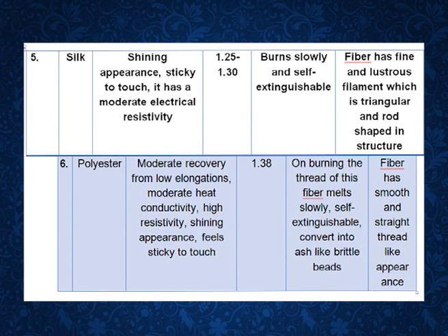Then is the polyester. Now it has a moderate recovery from low elongations, moderate heat conductivity, high resistivity, shining appearance, feels sticky to touch with a specific gravity 1.38. On burning, the thread of this fiber melts slowly, is self-extinguishable, converts into ash like brittle beads. Fiber has smooth and straight thread-like appearance.